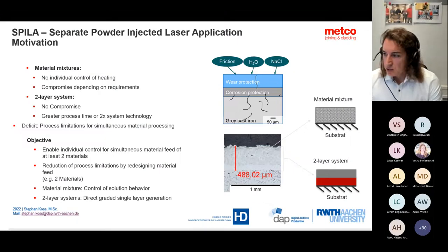Here, I would like to introduce a little bit deeper what type of nozzle developments go and why, what might be one of the directions. This is a project at Aachen University together with DAP Lab, and one good friend of mine, Stefan Koss, was leading this project. So imagine working with complex substrates like cast irons. Typically, if you need to protect them from wear and use metal matrix composites or other hard facings, it's very hard to avoid crack formation because cast iron itself is already a very hard substrate to work with. And if you put on a hard coating, you really might get in trouble, not only in terms of cracking, but also other defects.